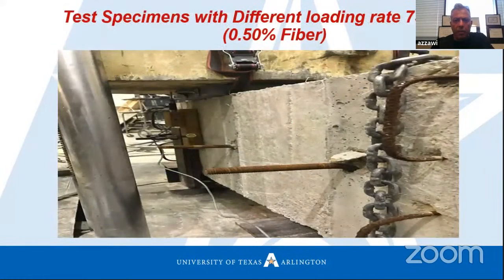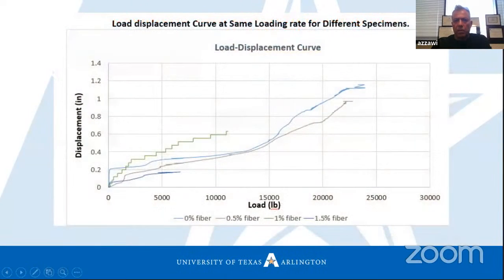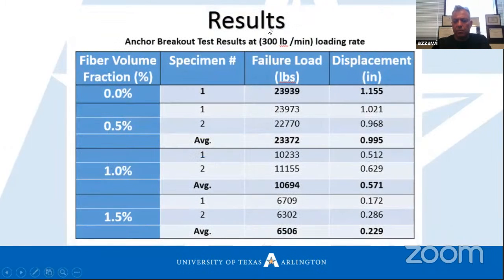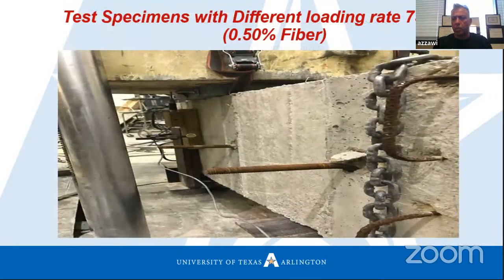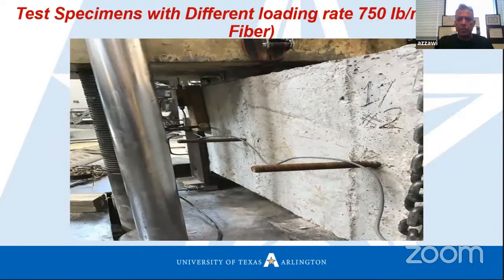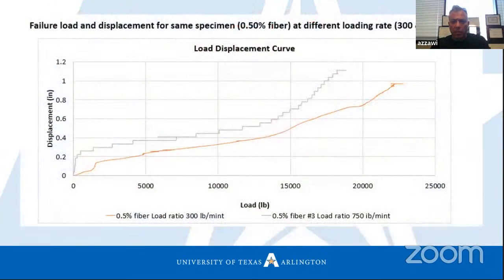Also, this shows us the test specimen with different loading. This is for 750 pound per minute. So we increased the rate from 300 pound per minute to 750 pound per minute, just to see if we change the loading rate, whether the failure load will change or not. We also did the same thing for the other specimens. We concluded that this is for the 300 pound per minute loading rate, and this curve is for the 750 pound per minute loading rate.